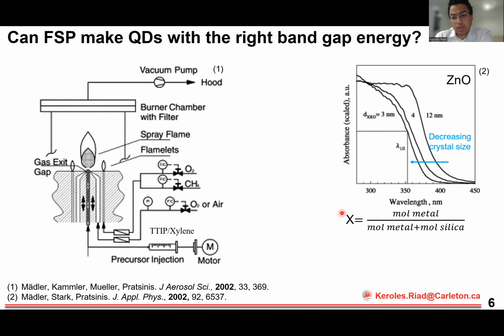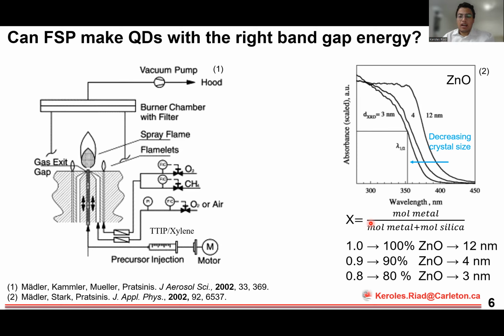And he reported the silica loading using a factor X, which essentially represents the percentage of the metal oxide. So X equal 1 is 100% zinc oxide, X equal 0.9 is 90% zinc oxide, and so on. As you see here, as X decreases, or the silica loading increases, the crystal size decreases. And in the plot, that means that the wavelength decreases and band gap energy increases. Now, even with the 3 nanometer crystal size, the absorption wavelength is still much higher than the 300 nanometers that I would like to get lower than.